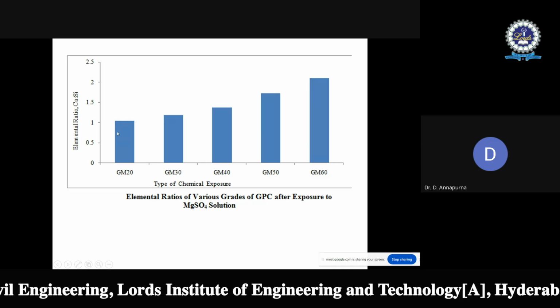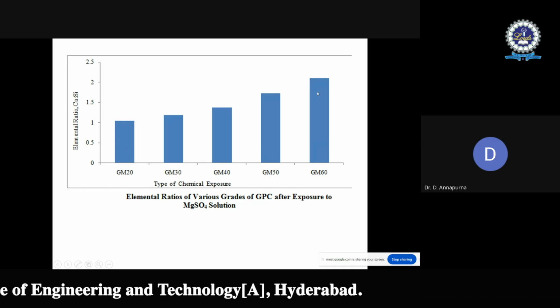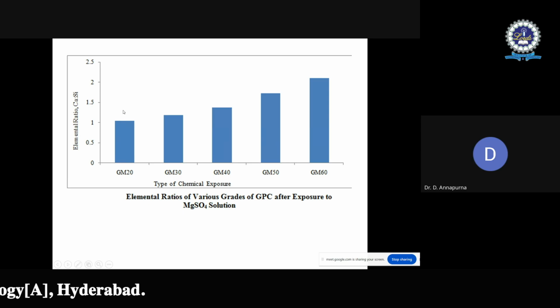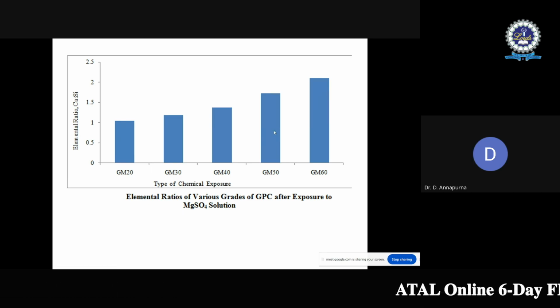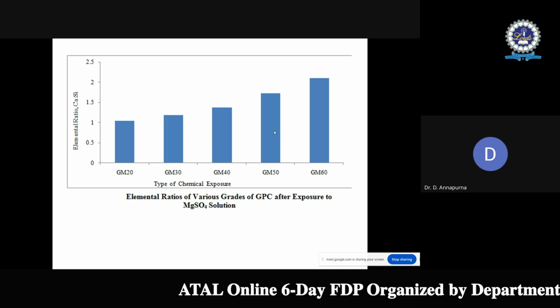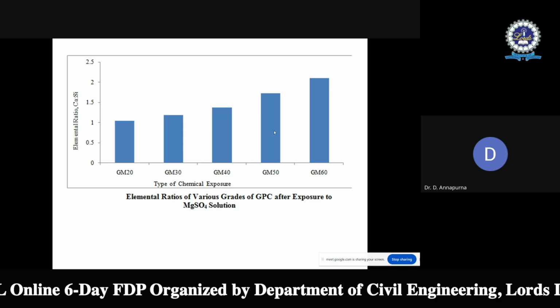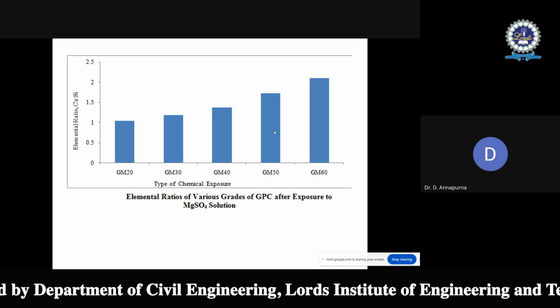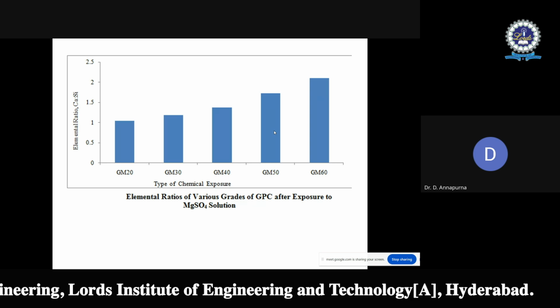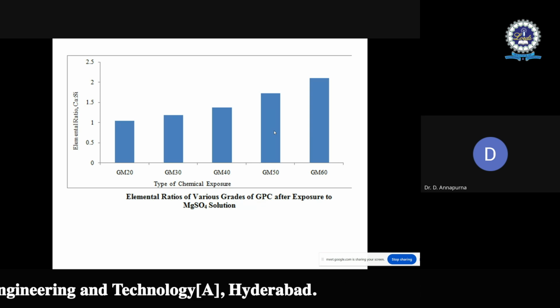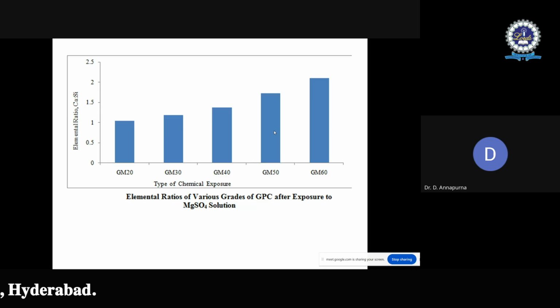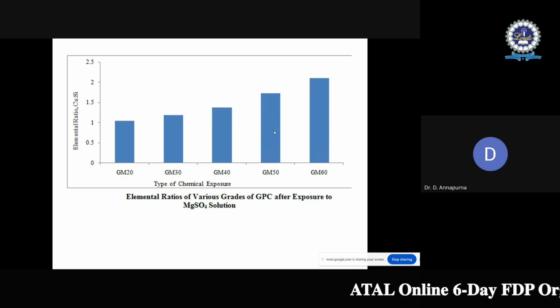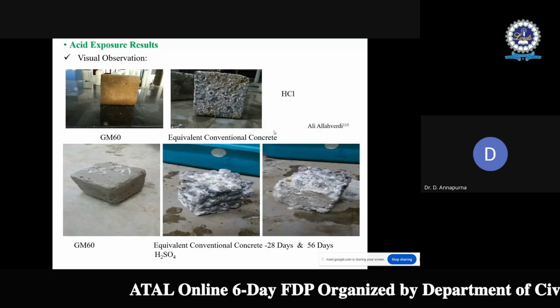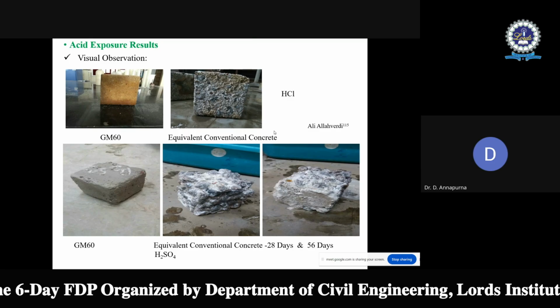If we look at the grades GM20 to GM60, the calcium by silicate ratio is increasing. But for the conventional concrete, the calcium by silicate ratios are increased by 26% and 30% respectively in sodium sulfate and magnesium sulfate solutions. So that is the reason we can say that all designated geopolymer concrete specimens show better resistance to sulfate compared to the normal concrete. Then the specimens are immersed in acid.